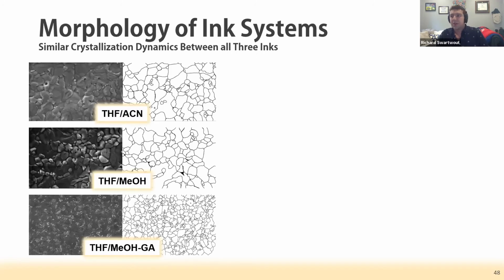One of the easiest things you can do is SEM-based analysis for morphology. If you look at the crystalline domains under SEM and pull out the boundaries as defined from SEM, there are 3 systems we looked at here: the binary mixture of THF and acetonitrile, THF and methanol, and then THF with a solution-based stabilizer.